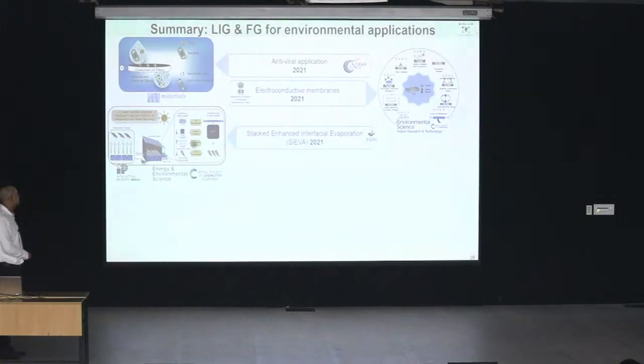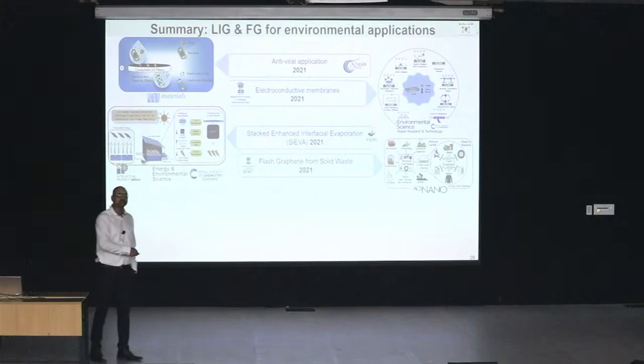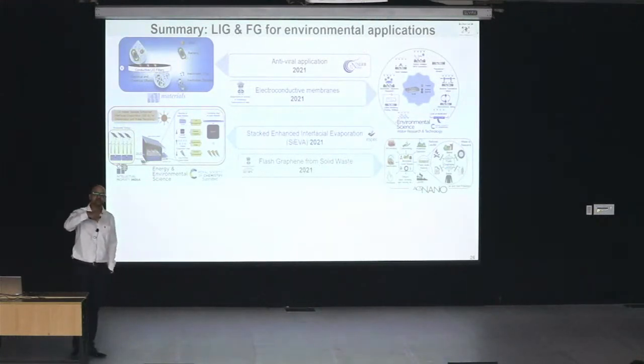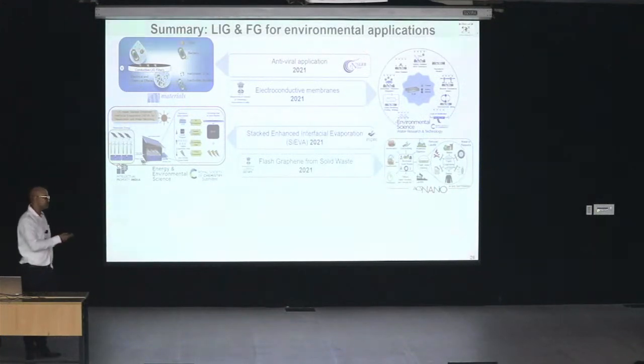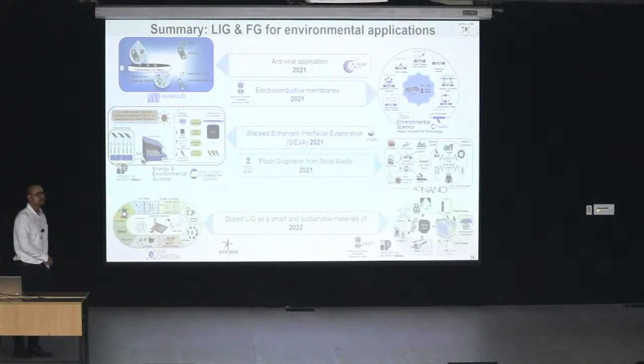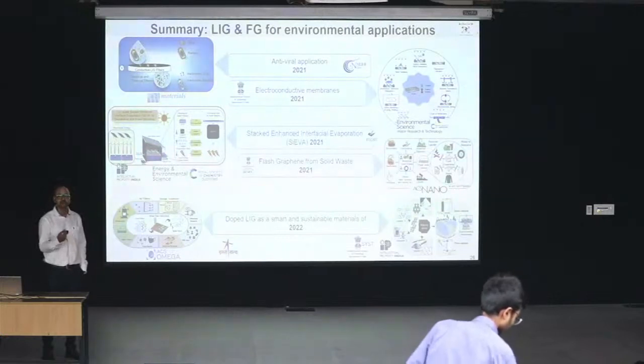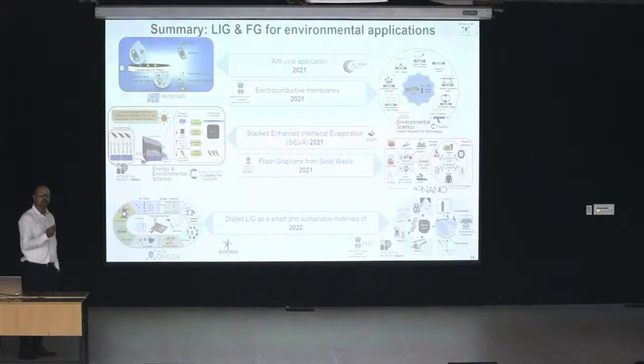Stacking can help us reduce the energy demand and footprint, and there is also another class of graphene which is inspired by this laser induced graphene. When we burn that surface, the laser gives almost 2200 to 3000 degrees of temperature, and we have tried to do the same thing with a normal electrical flash, where when we burn that surface in the presence of a light flash, it is converted into graphene. We have also demonstrated how these surfaces can be used for sustainable purposes, because in a single step we are converting these surfaces into graphene. We can also utilize different kinds of waste material to convert into laser induced graphene or flash graphene.